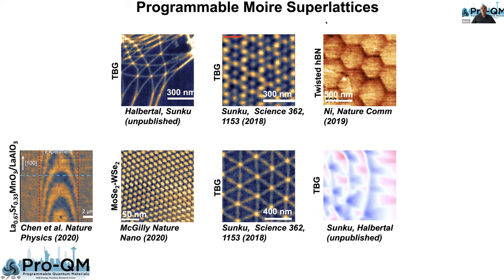I talked about polaritons already, but about plasmon polaritons, but you can do the same thing with lattice dynamics and with phonon polaritons. This hexagonal pattern shows a moiré superlattice in twisted van der Waals insulator. It happens to be hexagonal boron nitride. We coupled a broadband infrared laser to our nanoprobe, and we were able to see how phonon spectra are impacted by this superlattice.